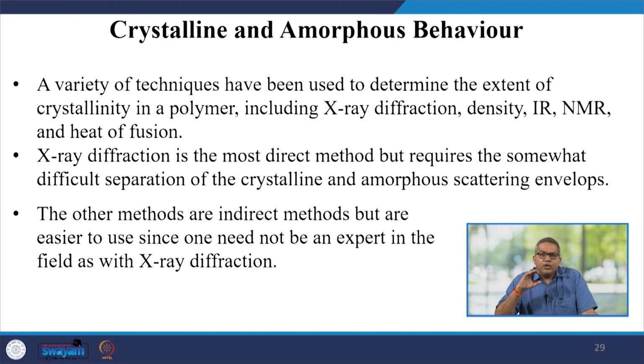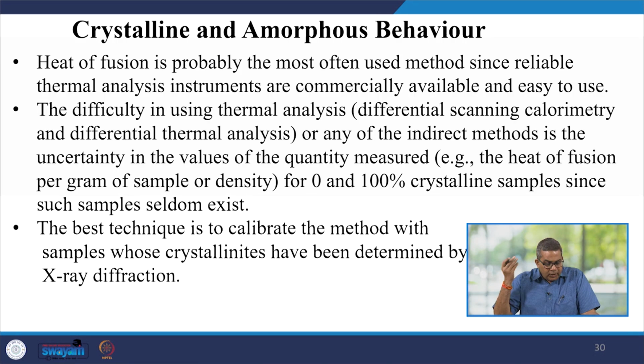crystalline state. A variety of techniques has been used to determine the extent of crystallinity in a polymer. This includes XRD or X-ray diffraction, density, infrared, NMR, and heat of fusion. XRD is the most direct method, but it requires a somewhat difficult separation of the crystalline and amorphous scattering envelopes. The other methods are indirect, but easier to use since one need not be an expert in XRD. Heat of fusion is probably the most often used method since reliable thermal analysis instruments are commercially available and easy to use.